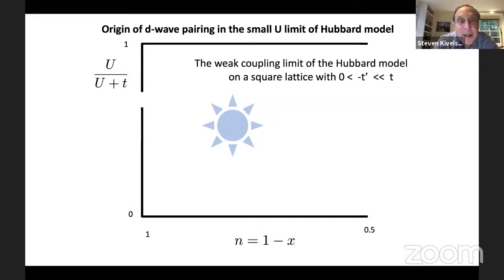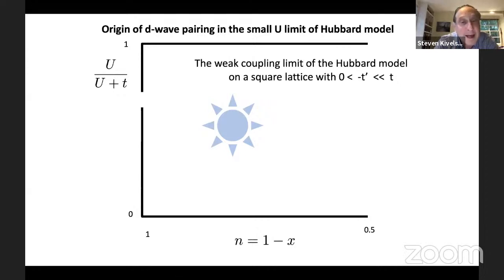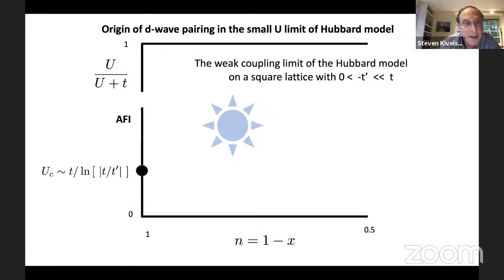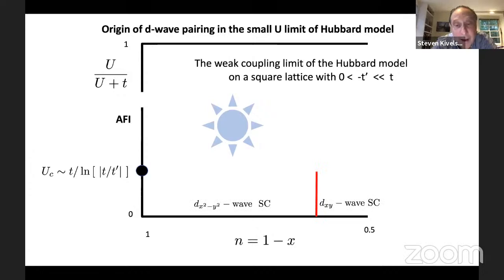Looking at what happens in the weak coupling limit, imagining going away from the perfectly nested case at half filling with a small second neighbor hopping T' to make the band structure look more like the cuprates: there is an antiferromagnetic insulating state at half filling that gives way to a metallic state below some small but finite value of U. All along the small-U axis of the phase diagram, we find superconductivity — d(x²-y²) superconductivity in a broad interesting region, and then maybe other forms of superconductivity at higher doping.